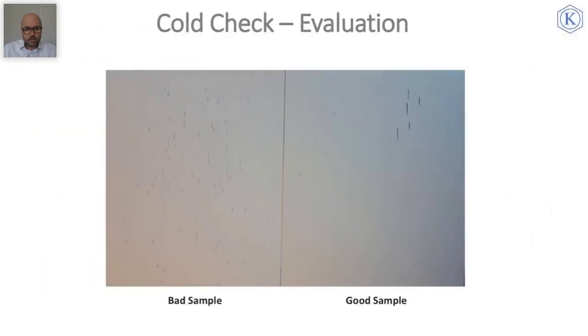Here is how it works. There's an example of a bad sample on the left-hand side and a good sample on the right-hand side. There are a couple of large cracks, but they are very low in number, and sometimes they are not very critical cracks. I don't know if it's visible, but there are dozens of tiny cracks here, which are indicated by colored pens by our colleagues in the lab. Of course, this is a relative test. There is a moment when the amount of cracks is too much on the wood surface, and we decide on the end of the test.